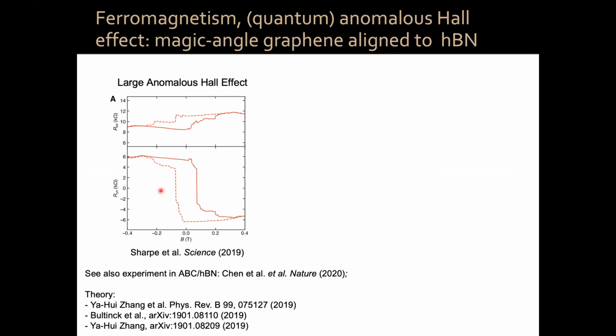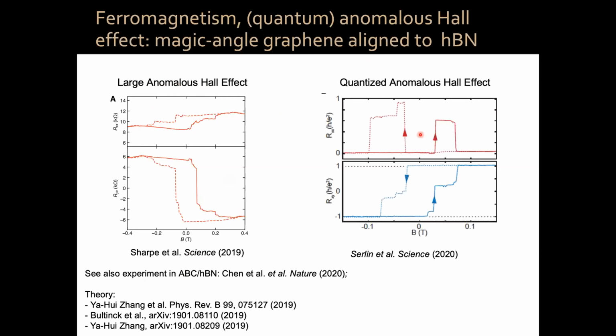And soon after, the group of David Goldhaber-Gordon reported this large anomalous Hall effect in magic angle graphene aligned to hexagonal boron nitride. When you align the magic angle graphene lattice to the underlying lattice, you break a symmetry of the system and you get this ferromagnetism. And a few months later, the group of Andrea Young demonstrated the quantized anomalous Hall effect in the system, making it clear that the system has very interesting topology.